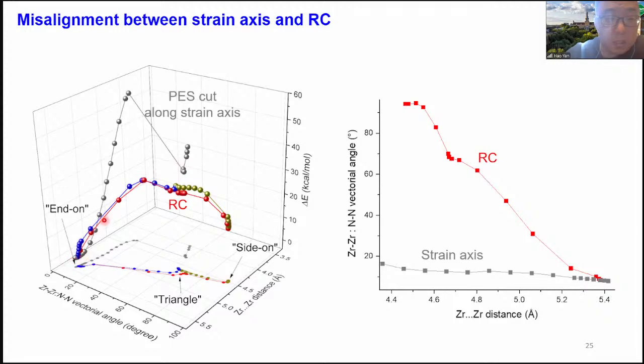So you see that without turning the nitrogen relative to the dizirconium axis, this slope becomes extremely deep and the barrier is extremely high, until it reaches some absurdly high energy, then it falls back to the intermediate triangle state, which then proceeds to the side-on structure.